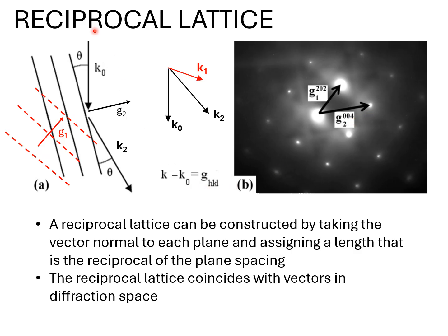When you look at the wave vector, if we define the wave vector of the incoming radiation by K0 and the scattered vector on Bragg diffraction, they would have these vectors. And the difference between the incoming radiation and the scattered radiation is actually the G vector, which is the reciprocal lattice vector, which would show up in the diffraction pattern. A lot to assimilate there, it needs some thought, and I'm not going to dwell on it any further except to wish you luck.